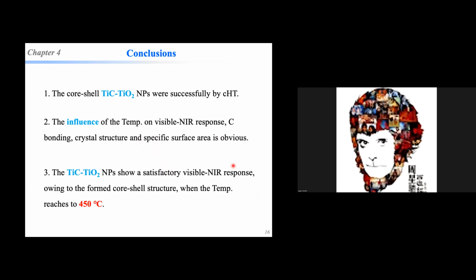And this shows the conclusion. This can come to these 3. And this one: the response and the core-shell structure can be formed or confirmed when the temperature is 450 degrees C for 1 hour, or with lower temperature and a little longer times. It can also form this kind of structure.